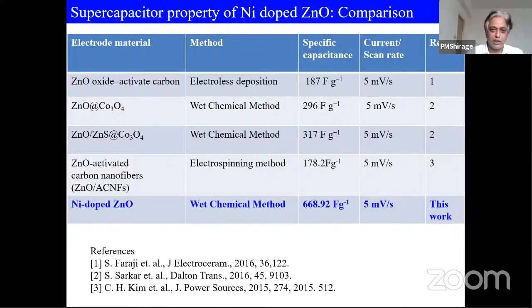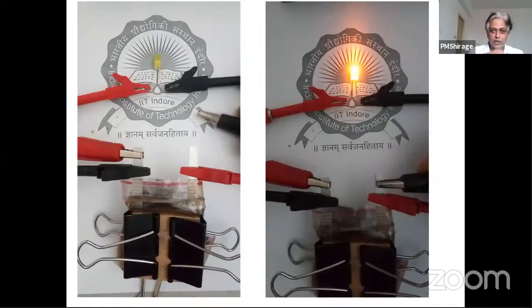Then another important application we tested was device making. We charged this supercapacitor for 10 seconds, and we lit this LED. This will light for 2 or 3 seconds, but this is good material. It is a small prototype device we prepared in the lab by using a polythene bag. You can also prepare it in your lab.